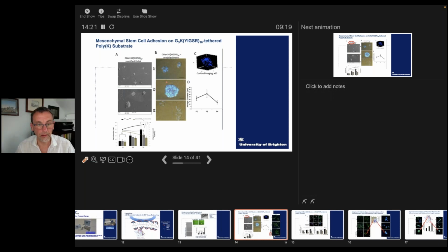And you can appreciate that basically these results were obtained when each of the nanotrees that I've shown in a schematic way in a few slides before were presenting 16 branches exposing the laminin sequence YIGSR to show how important the clustering of the integrin and the spacing of the YIGSR or any other peptide is in terms of cell response.